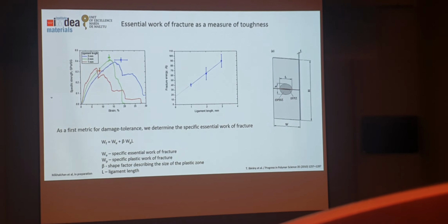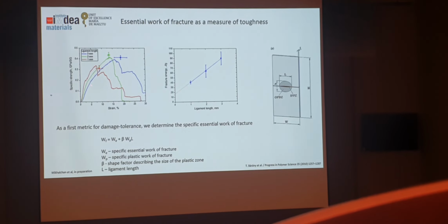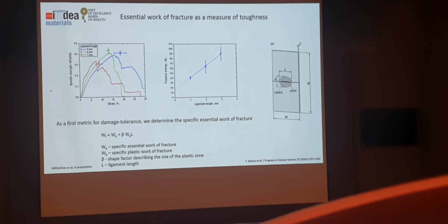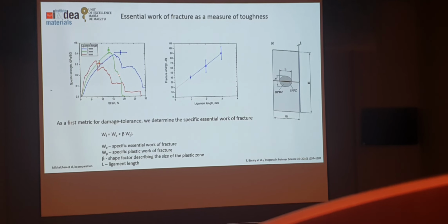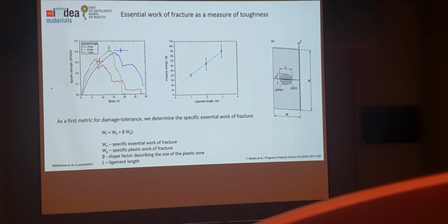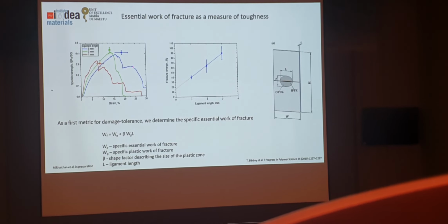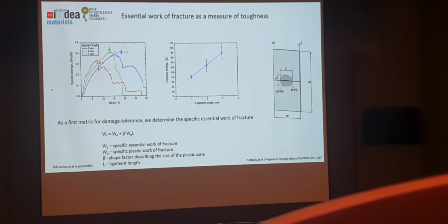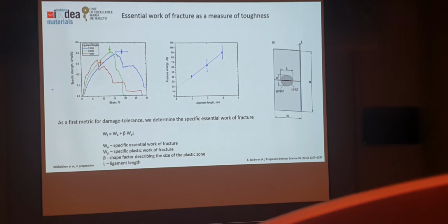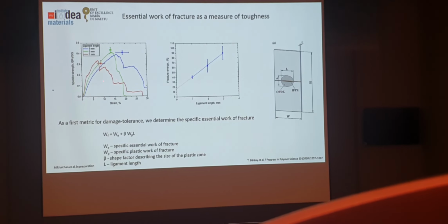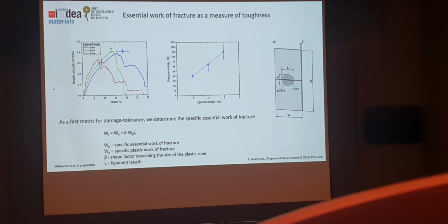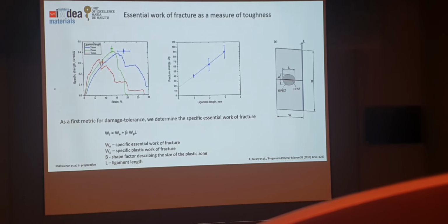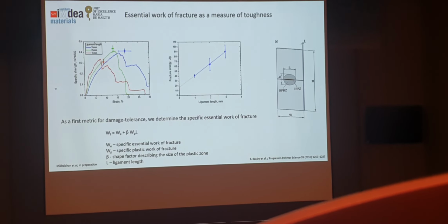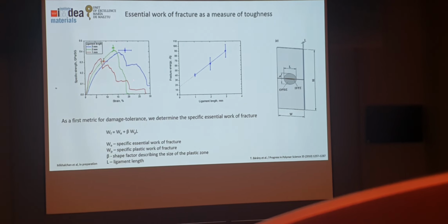And these are the results. So these are the stress-strain curves, and for different ligament sizes. We tested quite a few of them for each ligament size, but only a few ligament sizes. And you find that these are self-similar, which is normally a good sign that they behave like a polymer or a ductile metal. And you of course see this plastic deformation and energy absorption after they have yielded.